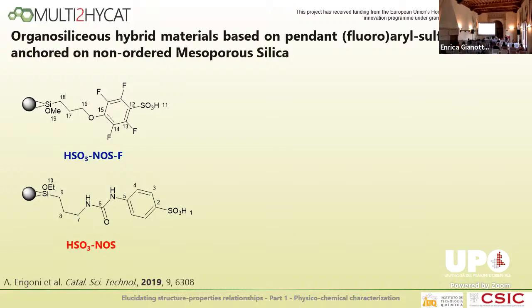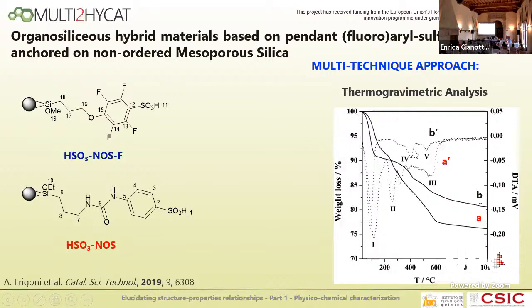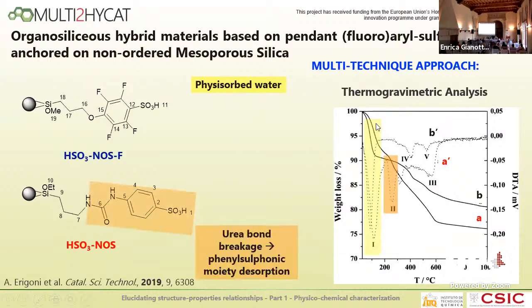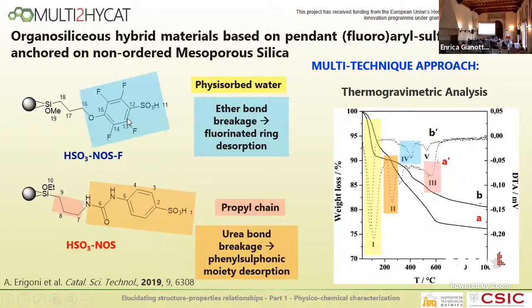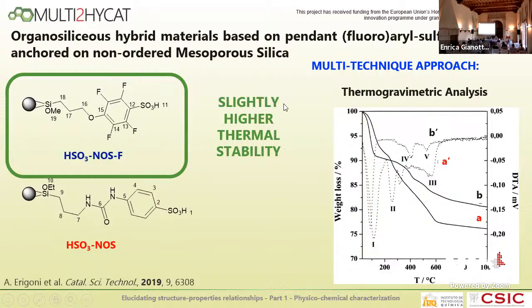First of all, I would like to drive your attention to the different thermogravimetric profiles that you already saw in Urbano's presentation. Beside a similar behavior in physisorbed water, you can clearly see different profiles, because the urea bond breakage, that is the connecting linking point for the non-fluorinated sulfonic acid, is at lower temperature with respect to the ether bond breakage that is characterizing the other hybrid. And this is bringing a slightly higher thermal stability of this hybrid catalyst, that is also connected, as we will see, with a slightly higher resistance to recyclability and in the catalytic conditions.